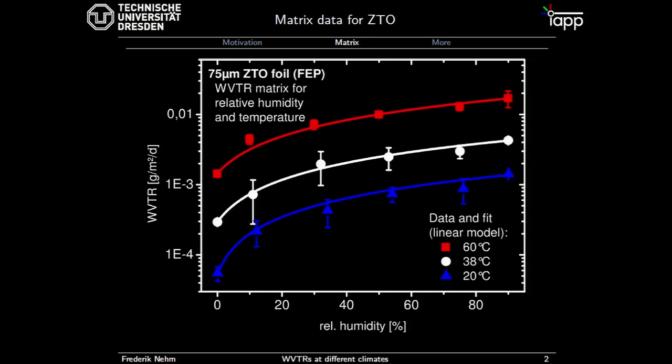So we can already say that for this kind of barrier, we are expecting absorption coefficients which are very much in terms of Henry's law. So the outside concentration of water in the air is directly, linearly proportional to the water concentration inside the test.